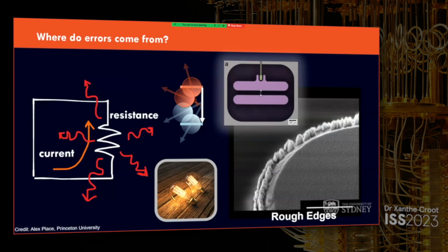Another materials challenge we face is how clean we can make the edges of this circuit. What you're looking at here is a scanning electron micrograph of the edge of one of these capacitor pads. Ideally, we have really smooth, beautiful edges, but what actually happens is we often end up, because of the etch chemistries that we use, with really rough edges. And these types of rough edges can mean that our circuit basically dissipates energy in those edges where we don't want it to.